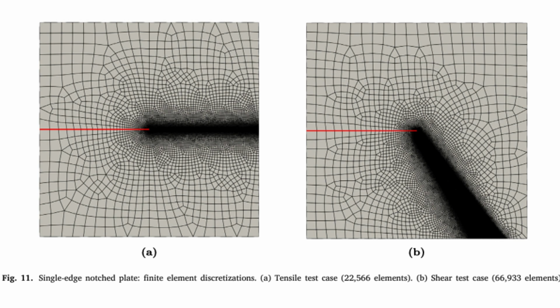Sure. So phase field modeling is actually quite an elegant solution to a tricky problem. Tracking a physical crack, a sharp discontinuity that suddenly appears and grows, is computationally very difficult, especially in complex 3D shapes. You'd have to constantly remesh or track the crack tip explicitly. Precisely. Very messy. So phase field takes a different approach. Instead of a sharp crack, it approximates it as a narrow, diffuse region. Think of it like smearing the crack out over a very small width. Okay, like a fuzzy crack instead of a sharp line.